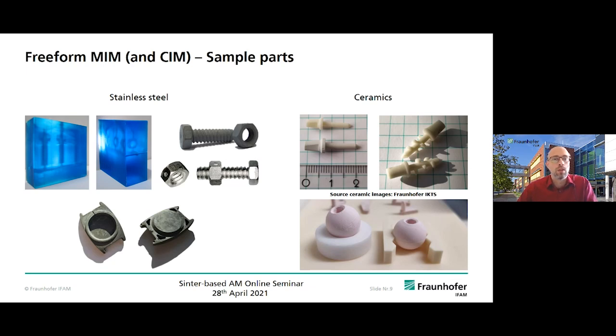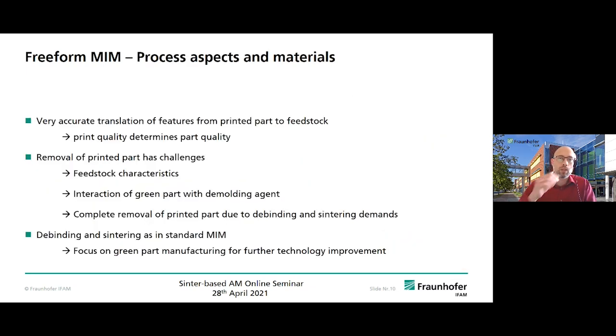And we also looked into geometries in this case. On the right side, you can see some examples with ceramic materials that were done by our colleagues from IKTS. And we see a very interesting process there. Some aspects I want to share are that we have a very, very accurate translation of the print part features into the green part of the feedstock. So really this print part quality is what mainly determines your sinter part quality in the end.